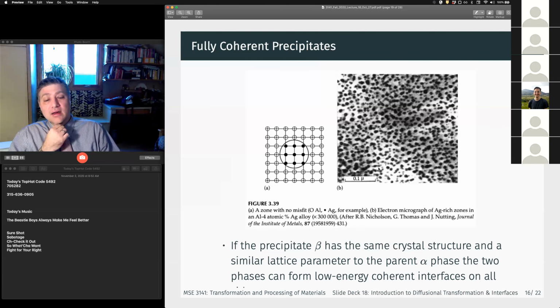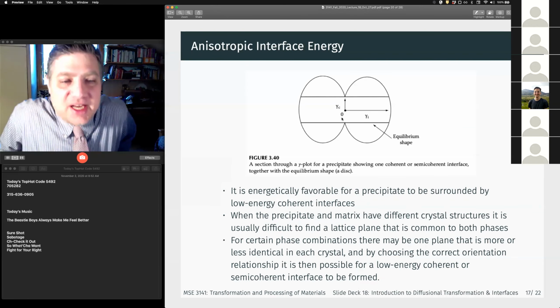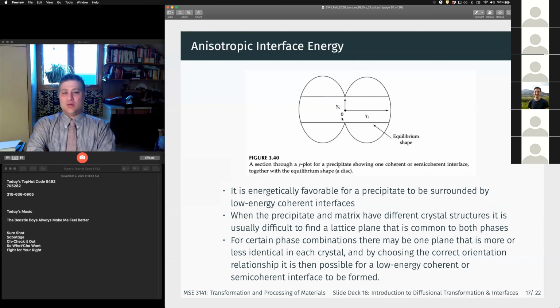But what we see is that when everything works out, these can form low energy, fully coherent interfaces, and the precipitates will tend to take a perfectly spherical shape. And the spherical shape is because that is going to minimize the surface area to volume, and so we can take the lowest energy in our system. Our system can adopt the lowest energy by making spherical particles. If our interfacial energy is anisotropic, we're going to get different shape precipitates.